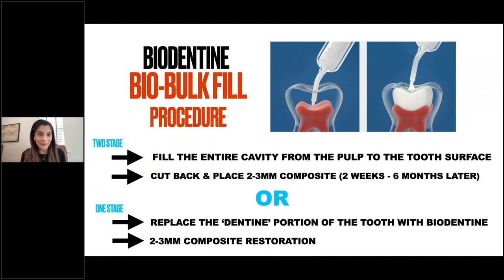However, if you're like me, I quite like to get things done in one visit. So I usually go for the one-stage procedure. That means that you use Biodentine in a much thicker section. So you use it to replace the dentine portion of the tooth. So not like the thin layer that you saw me just do, but a bigger, thicker layer. And then you leave 2 to 3 millimeters of space on top. And once the 12-minute set has done, you then place that composite layer straight away.